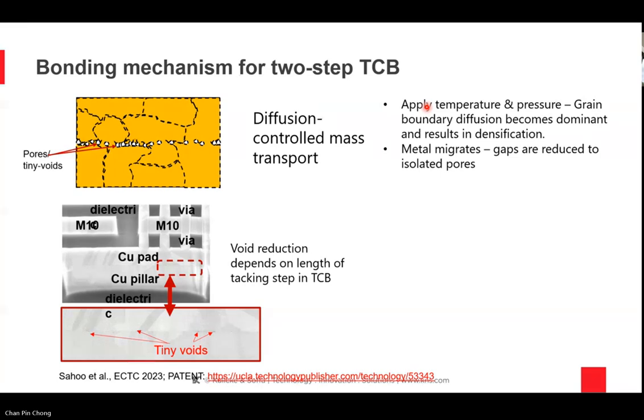This process is very similar to what happens in hybrid bonding as well, except the method in which we apply force in TCB is an externally impressed force, while in hybrid bonding it is thermally induced force caused by the expansion of copper. But the fundamental mechanisms are very much the same. You end up with these voids, and these voids have to disappear by further diffusion, and you can get rid of most of them.